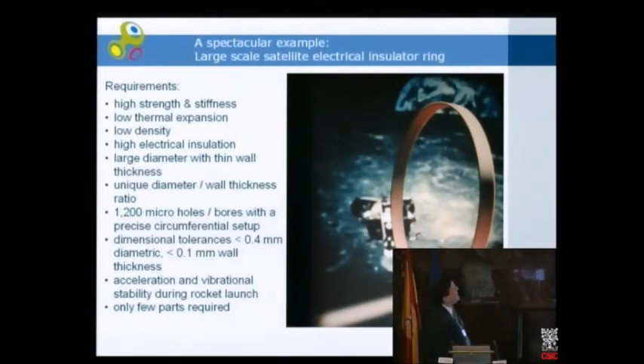with a total diameter of about 80 centimeters. And with this diameter, you may guess what the dimensional tolerances are to have a very precise ring structure with such a relatively thin wall thickness. What you cannot see from the chairs behind is that this structure contains 1,200 micro holes, micro bores. How to produce such a part?